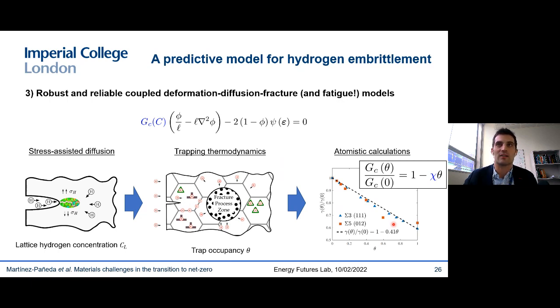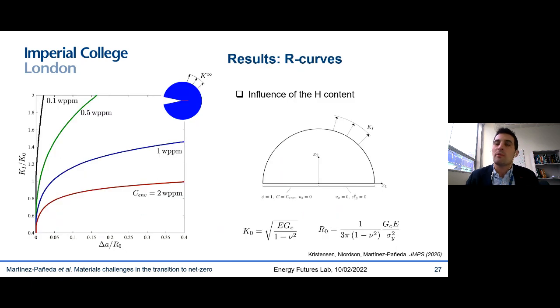So that's quite exciting. So let me show you some results. These are what we call R curves, crack growth resistance curves. What you see here is the applied load, and this is the crack extension. And you see, a measure of the applied load. And you see basically the trend that you expect in the experiments.